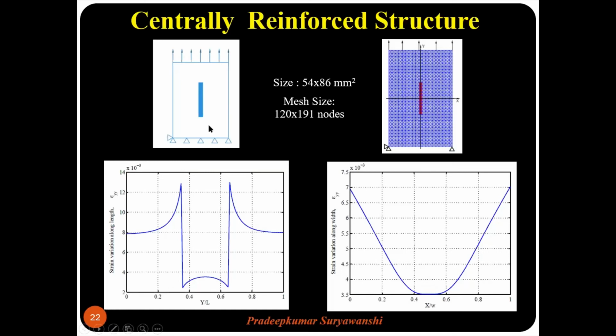So we observe that along the length, when we move from bottom to top, there is an increase in strain as we approach the inclusion, and at the tip of the inclusion it is maximum. There is a non-linear increase in the strain value, and at this position it is the maximum. As soon as we enter the reinforcement, there is a drastic reduction in the strain values, and very minimal strain is there. Then at the tip again it increases to the maximum, and increases in this way as we move to the top of the structure.